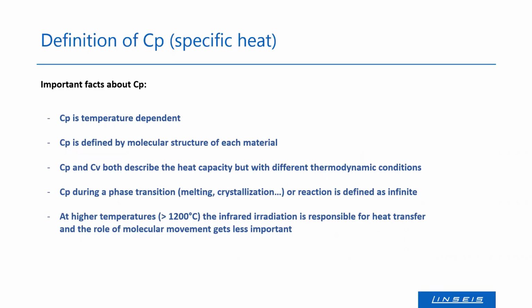Of course, the CP is temperature dependent. Otherwise, it doesn't make sense to heat it up with the DSC, I think. And it itself is defined by the molecular structure of the material. And yeah, CP and also CV with constant volume describe the heat capacity under different thermodynamic conditions. An important thing we will focus on later is that the CP during a phase transition, like melting or crystallization, is defined as infinite. So we cannot say, okay, the CP in this melt is 3 joule per gram Kelvin or something like this. That would be important later, I think.